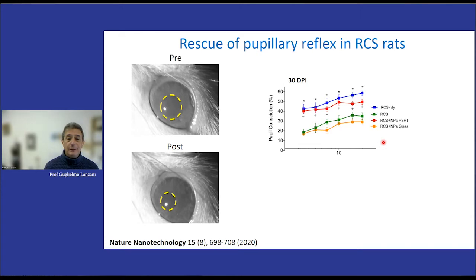We did an experiment with 4 different kinds of samples. Those animals that are, say, healthy are the blue data. Those animals that are affected by the disease are the green ones. The animals that have been operated with glass nanoparticles, just as a sham operation, this is to test that indeed it is not a natural response that we are looking at. So for surviving photoreceptors, for instance, the result would be the same when you put glass nanoparticles or our nanoparticles. So if surviving photoreceptors are responsible, this experiment should also give an answer. It doesn't. And then in red, you see our operated animals. And you see very well that we are able to rescue pupillary reflex almost completely.